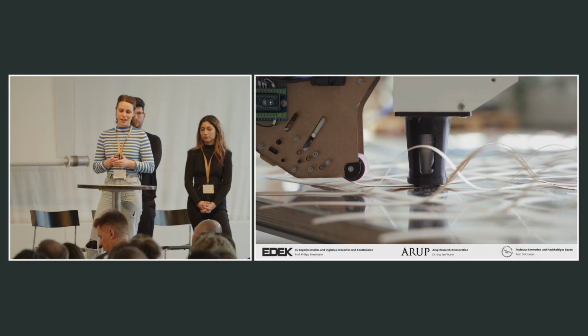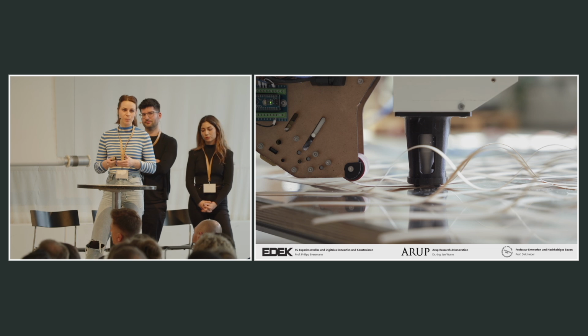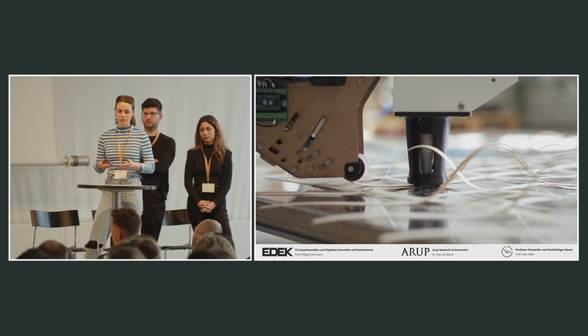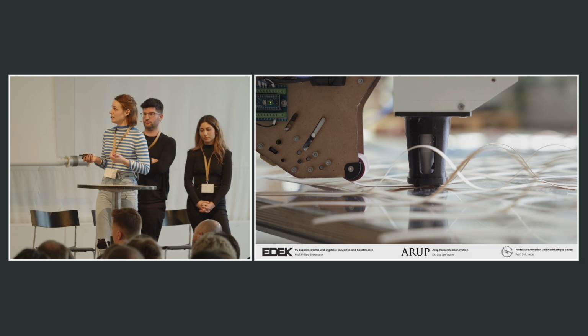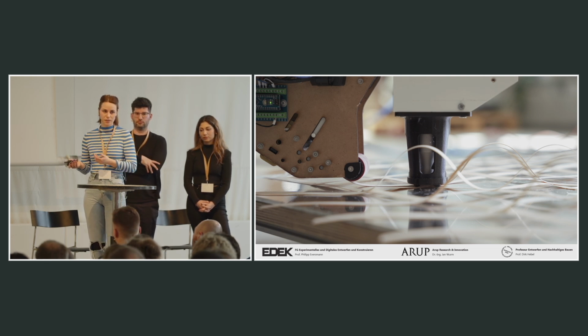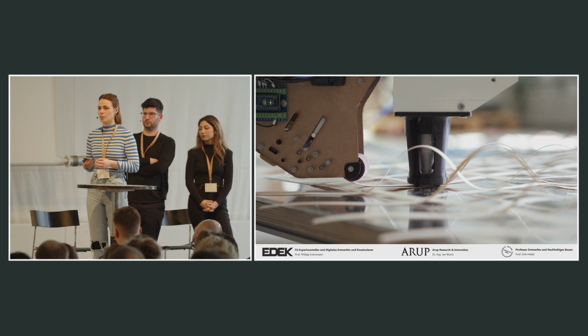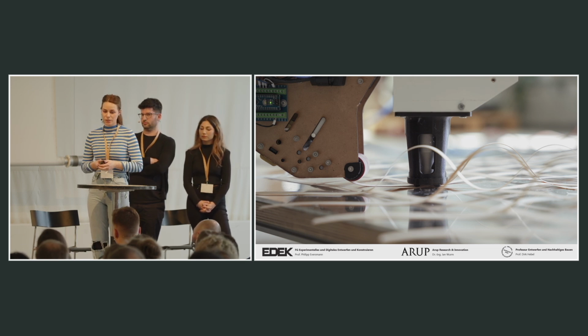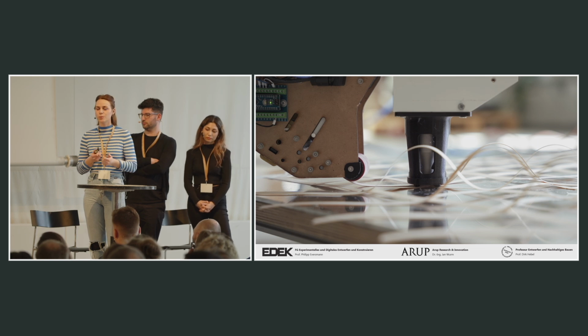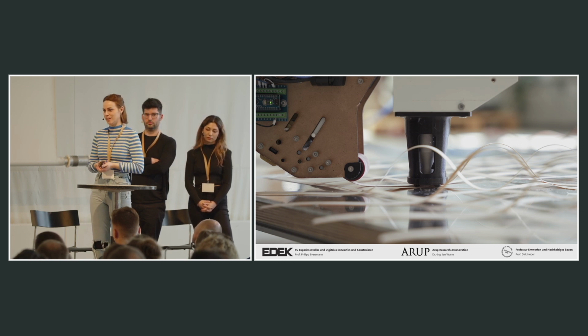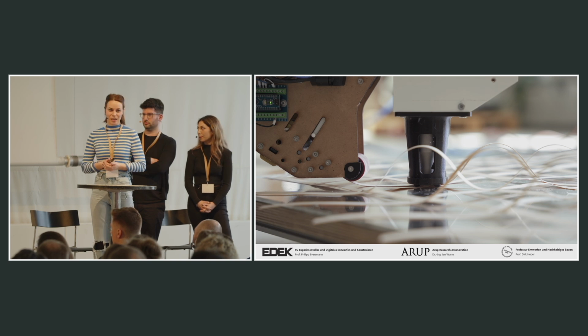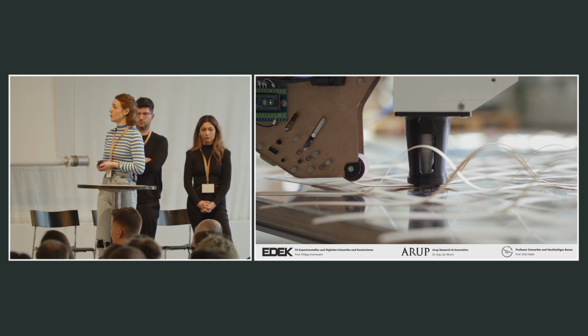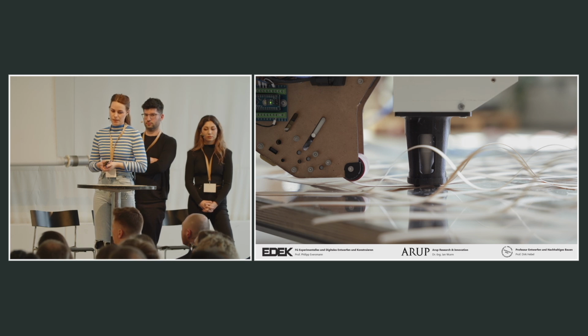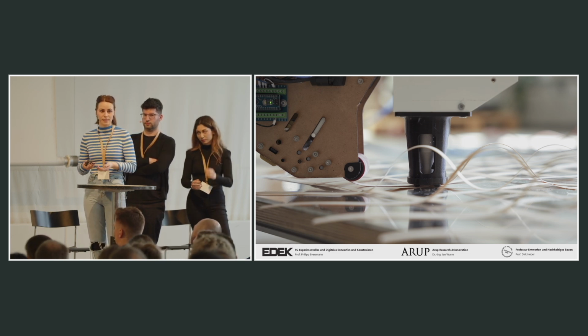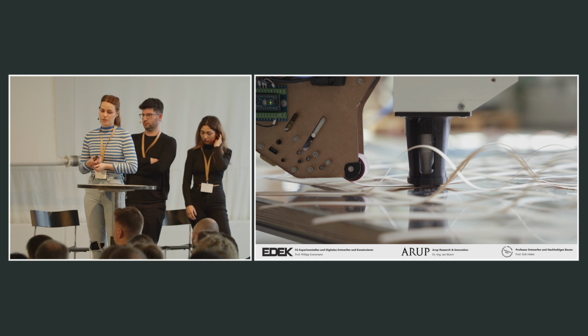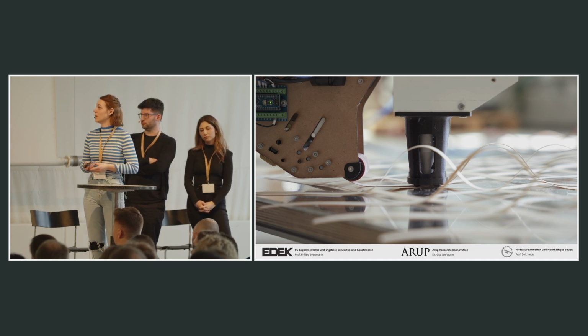A key challenge during our development was the identification of a bio-based binding method that would keep up with the process speed. Most bio-based binders either require long curing times or they require to coat the veneer completely in the binder, which would negatively influence the veneer mycelium bond strength. Hence, we avoided using any binder and we introduced an ultrasonic welding process, which is usually applied to thermoplastics, and it is economical and automated and well suited for mass production.